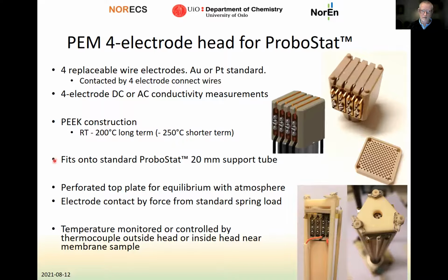As I said, this fits onto a standard ProboStat, 20 millimeter outer diameter support tube. It has a perforated top plate that we press down using the spring load. This allows equilibrium with the atmosphere via the perforation here. And it forces contact between the polymer film and the electrodes here by using the force of the standard spring load.